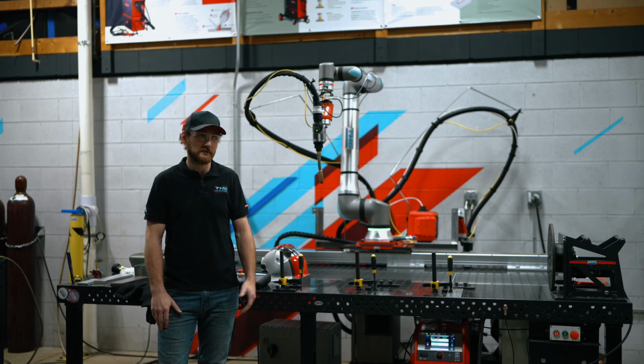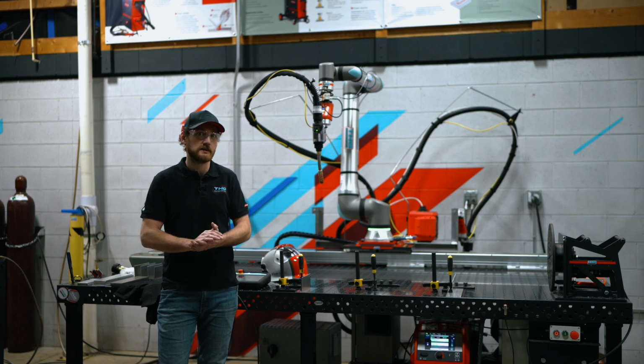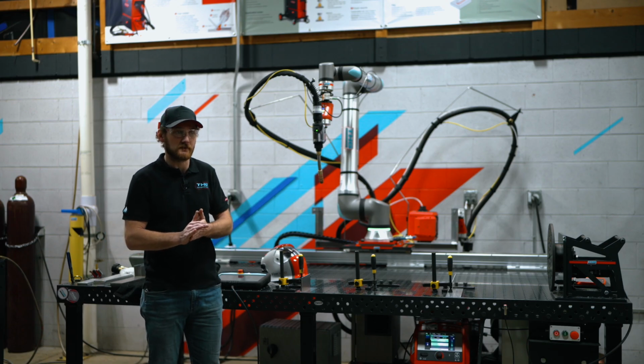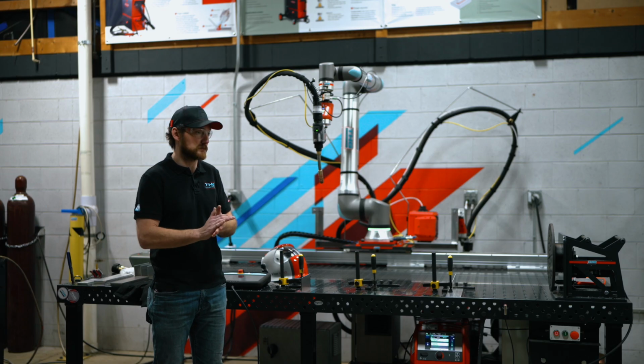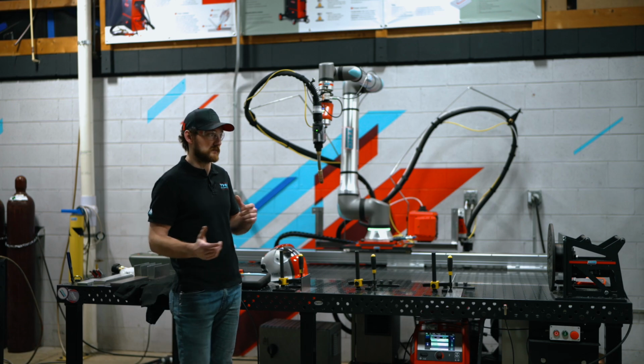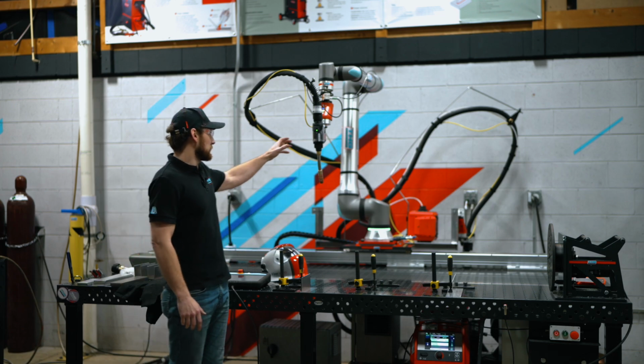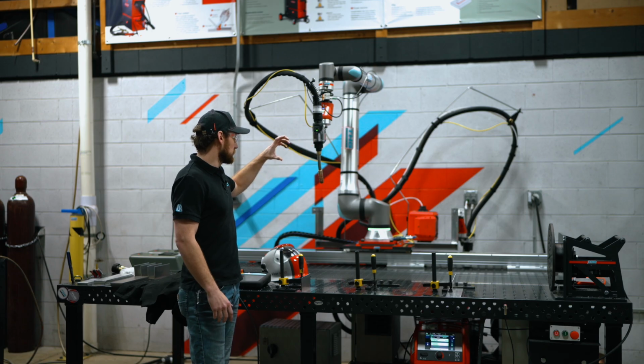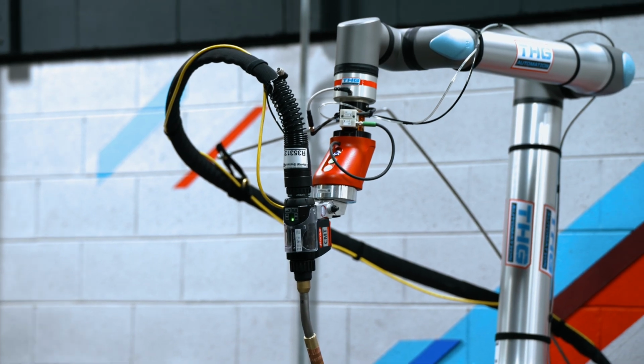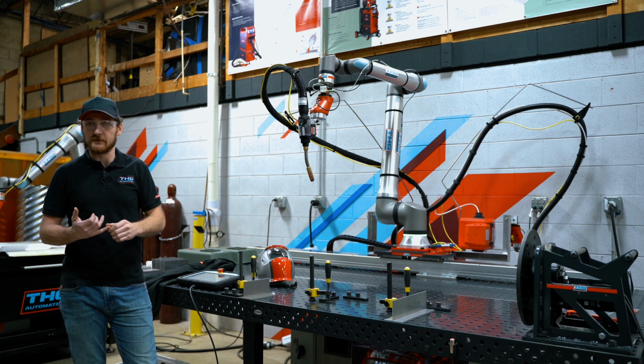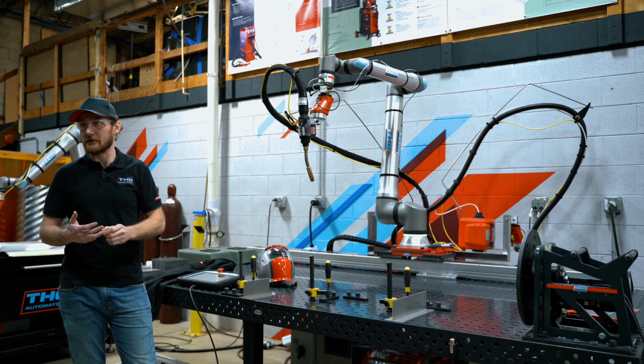One of the biggest challenges with welding aluminum, specifically with MIG, is typically the feeding. With other systems, besides the Fronius push-pull that we have behind us, you run into either bird's nesting or wire slippage. With the Fronius equipment, you actually have a push-pull system which eliminates a lot of those feed-related issues. So you can run softer wires like 4043 and 030, 035 wires, 045 up to 062.